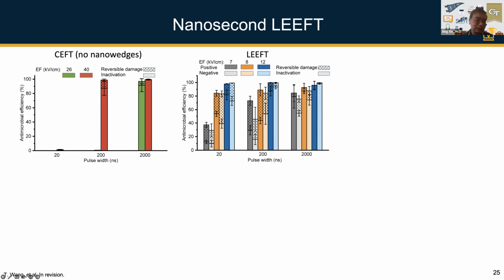Theoretically, for the conventional electric field treatment, that's the one without these nano wedges, just the flat electrode, usually we consider 2 microseconds. Okay, so it's already the limit. So 2000 nanoseconds is 2 microseconds, because you really need to have enough time for the ions to move and then squeeze the membrane and cause inactivation. If you want to shorten that to 200 nanoseconds, the voltage needs to be significantly higher, and then you'll still be able to do that. But if you shorten that to 20 nanoseconds, the ions barely move, and theoretically you just cannot achieve any inactivation.